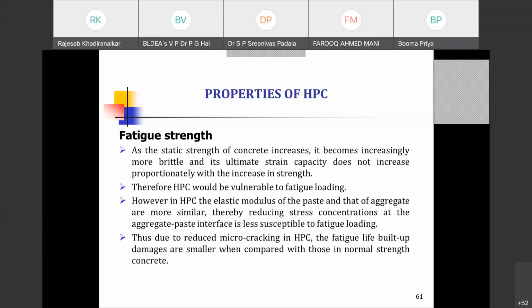since it is brittle, its ultimate strain capacity doesn't increase proportionately with increase in strength. There is an increase, but it is not proportionate. And then in HPC, the elastic modulus of the paste and that of aggregate are more similar, thereby reducing the stress concentrations at the aggregate paste interface, and it is less susceptible to fatigue. So thus, due to reduced microcracking in HPC, the fatigue life built up damages are smaller when compared with those in normal strength concrete.